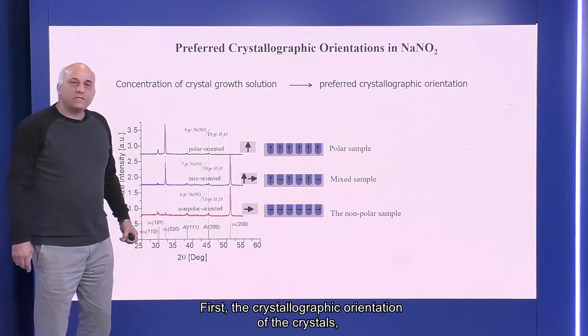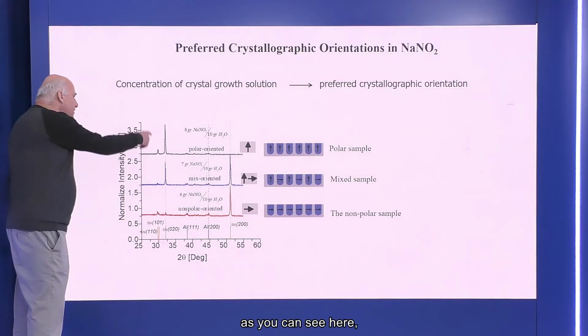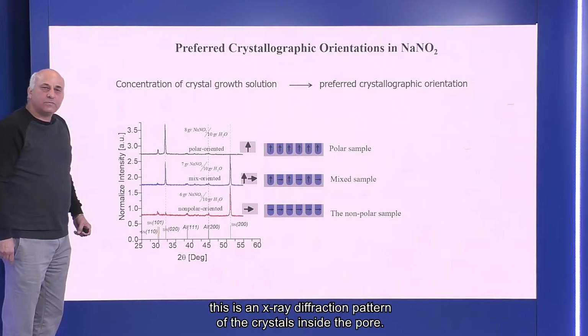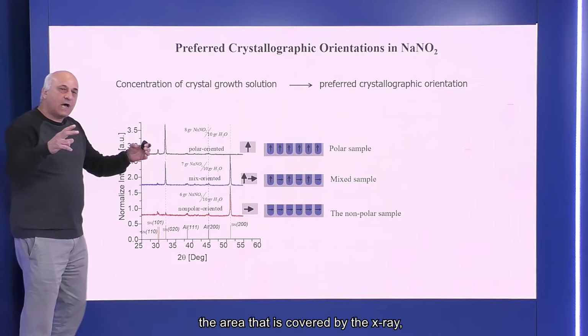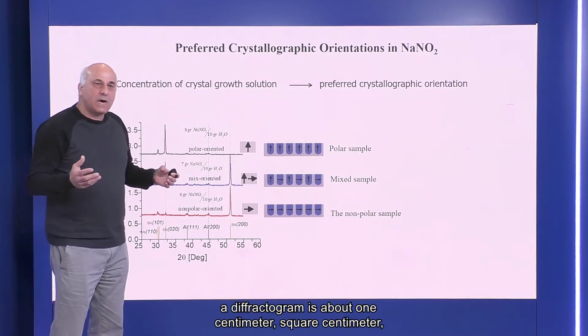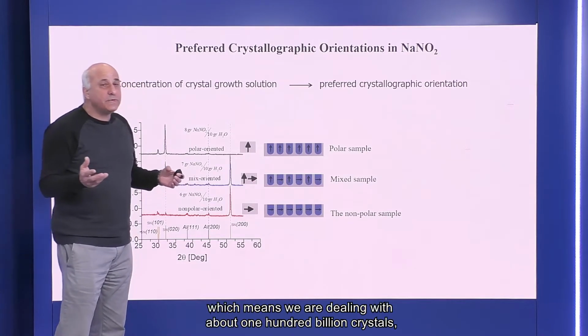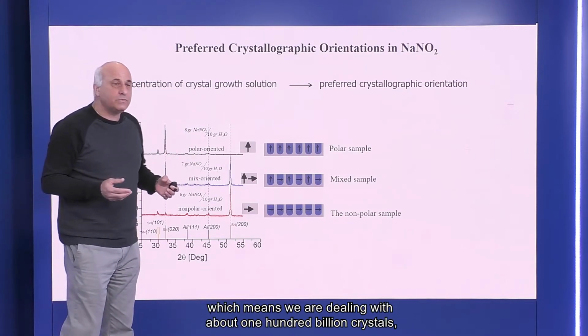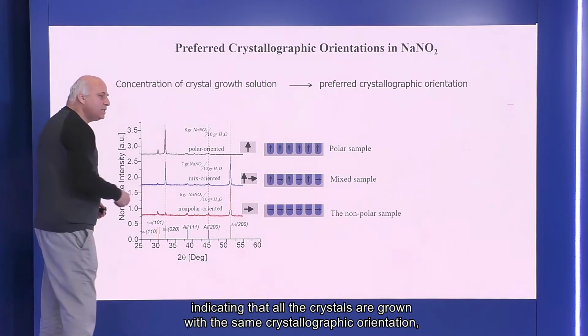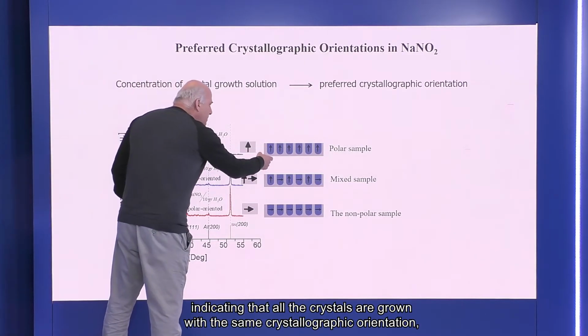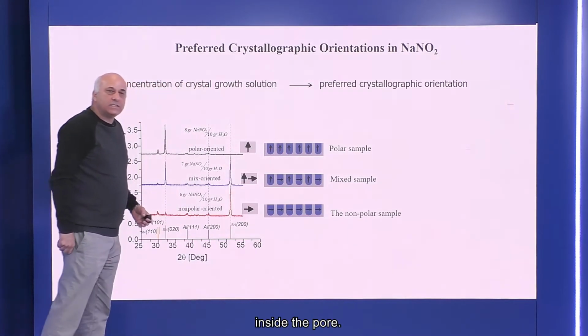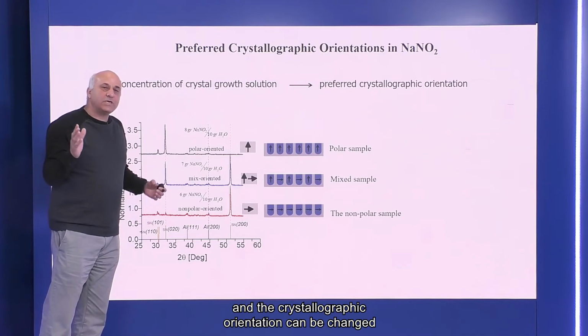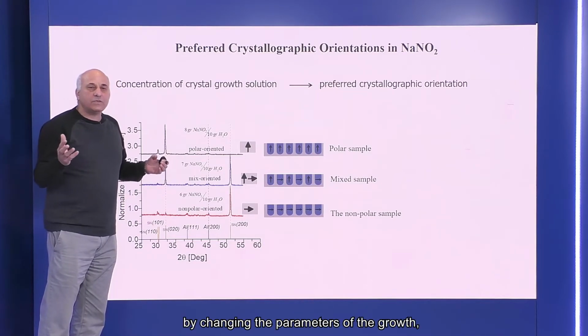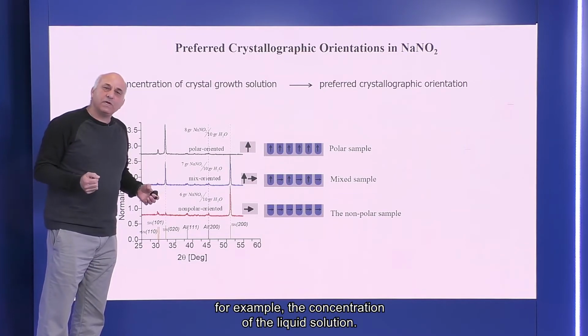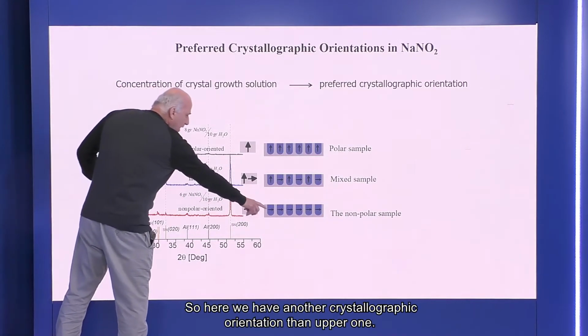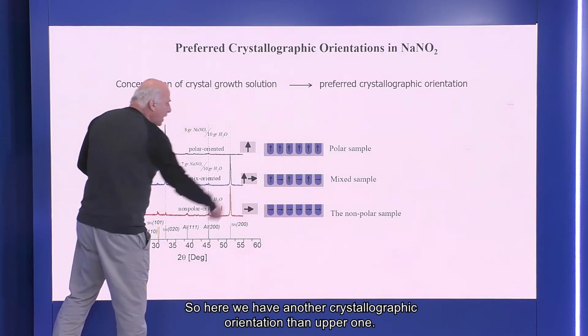First, the crystallographic orientation of the crystals. As you can see here, this is an X-ray diffraction pattern of the crystals inside the pores. The area covered by the X-ray diffractogram is about 1 square centimeter, which means we are dealing with about 100 billion crystals. You can see here only one peak, indicating that all the crystals are grown with the same crystallographic orientation inside the pores. And the crystallographic orientation can be changed by changing the parameters of the growth, for example, the concentration of the liquid solution. So here we have another crystallographic orientation than the upper one.